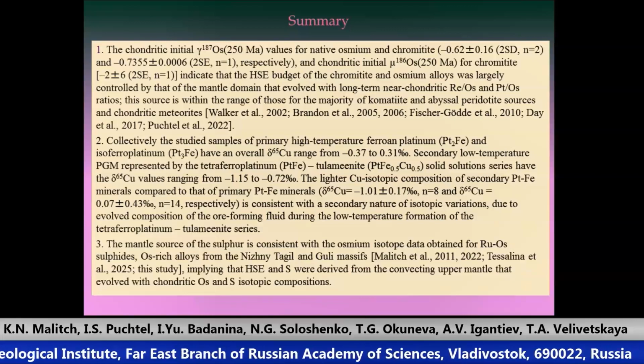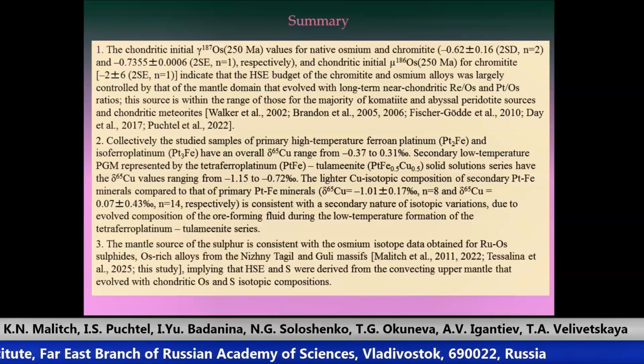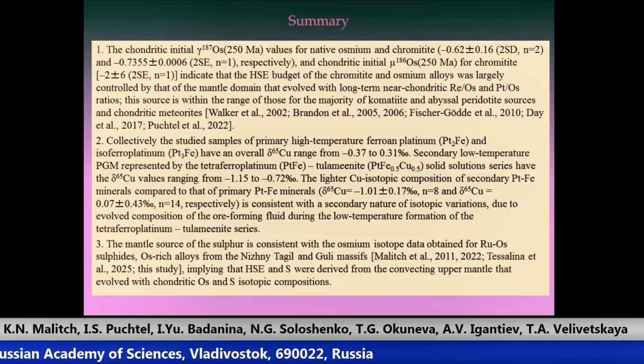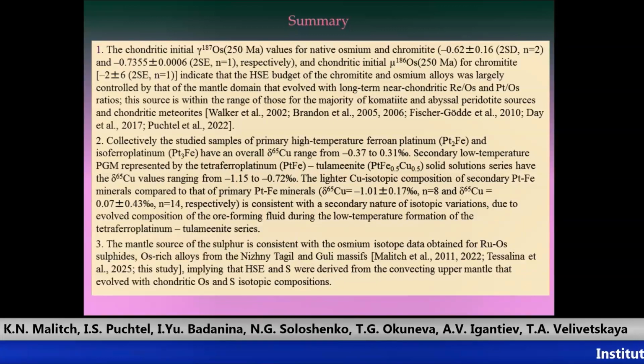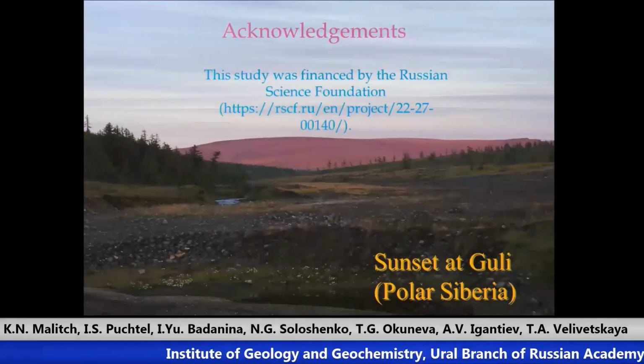Finally, the mantle source of the sulfur is consistent with the osmium isotope data obtained for ruthenium-osmium sulfides, osmium-rich alloys from the Nizhny Tagil and Guli massifs, previous studies, and this study, implying that highly siderophile elements and sulfur were derived from the convecting upper mantle that evolved with chondritic osmium and sulfur isotopic compositions.